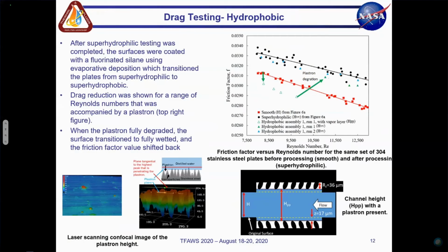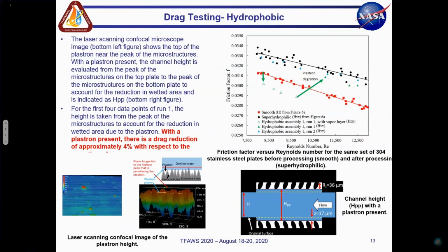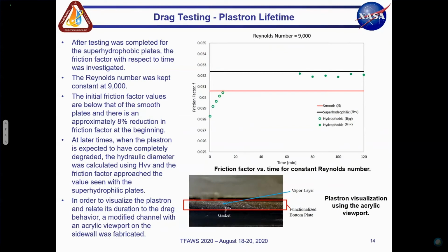So as we talked about, using a Keyence microscope, we're able to get that the plastron itself is roughly at the tips of the microstructures, and so getting the height of the channel or the wetted area, we go from the peak of the microstructures to the peak of the other microstructures on top, and that's how we adjust that. Now, as the plastron degrades, we evaluate it from a fully wetted, so an HVV, height valley to valley, as I talked about in the previous slide. So for the first 4 data points where we saw a plastron, we get roughly a 4% drag reduction with respect to the smooth surface.